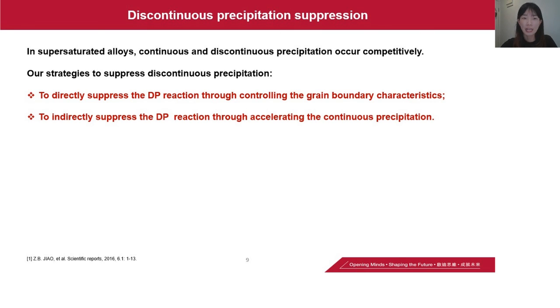How to suppress the discontinuous precipitation? We know that in supersaturated alloys, continuous and discontinuous precipitation occur competitively. So maybe we could use the continuous precipitation to suppress the discontinuous precipitation. And on the other hand, we can control the grain boundary characteristics to control the occurrence of the DP reaction.